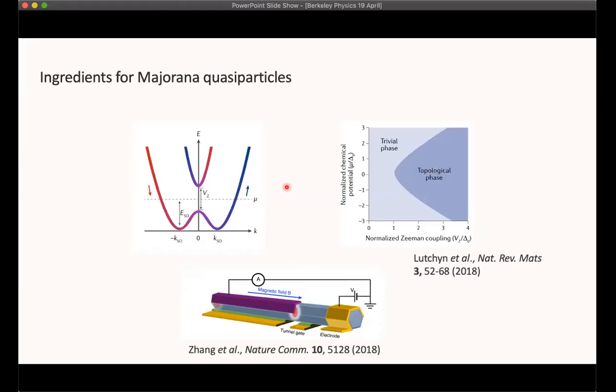Fermi points. And so in the presence of all of these ingredients, we establish a phase diagram like the one shown here, where for many points in phase space, we have a trivial superconducting phase. This is very akin to, in the Kitaev model I showed, all of the pairing of Majoranas happening on their individual sites. But by tuning the Zeeman energy and the chemical potential, we can actually observe that there is a topological transition into a topological phase where now we expect those unpaired Majoranas at the ends of the wires. And that's what these little pink ghosts are supposed to be in here, where the end of the wire is where the end of the proximity effect is, where the superconductivity stops, even though the semiconducting nanowire continues.